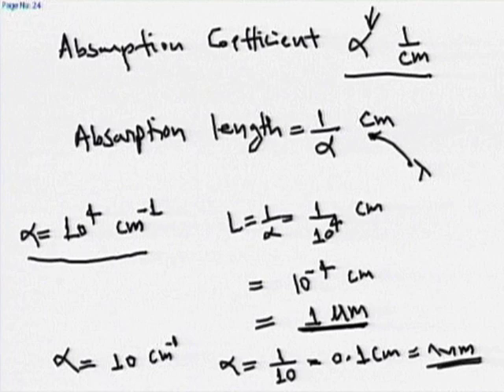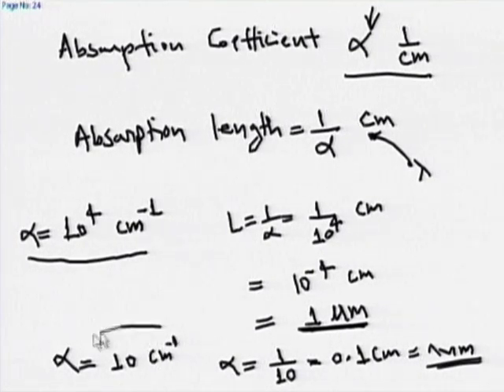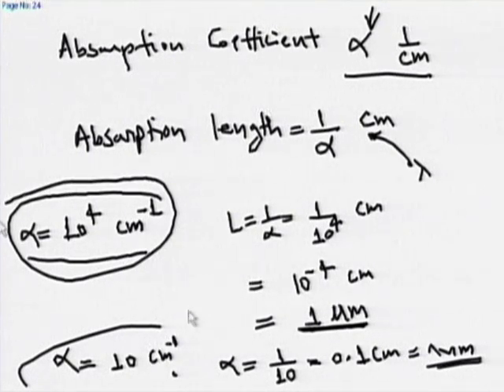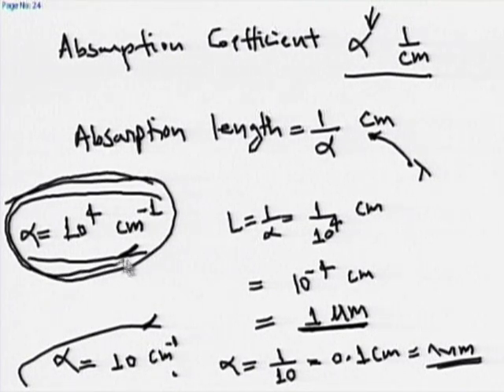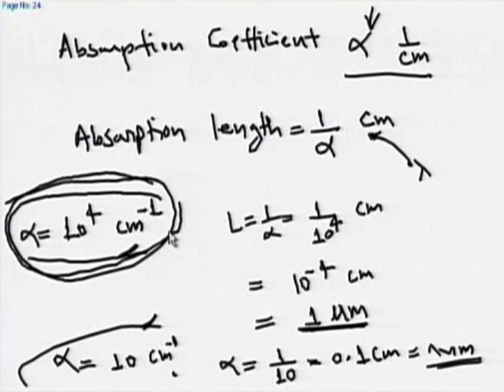All light with low absorption coefficient — remember absorption coefficient is a function of wavelength — for that kind of photon you require 1 micrometer material; for another kind you require 1 millimeter material, which is too thick. Thin film solar cells are either 1 micron, a couple of microns, or less. So all materials for thin film solar cells must have absorption coefficient higher than 10⁴/cm. If your absorption coefficient is 10⁴/cm, then only 1 micron is needed.